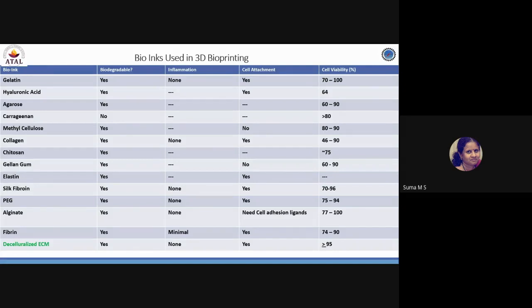Most of the bioprinting with respect to bone bioprinting was done by taking collagen as the bioink, in combination with another biopolymer, hyaluronic acid. Hyaluronic acid is extremely hydrophilic and helps in the sticking or adherence, and the presence of hyaluronic acid also facilitates or increases cell attachment. But the disadvantage here is that hyaluronic acid does not have an ideal consistency. So that is why it is used in combination with collagen, and there is research where bone materials are printed using these two biopolymers.